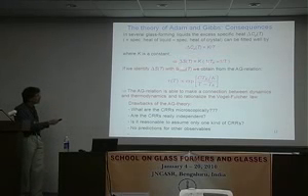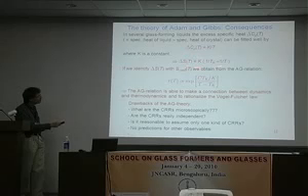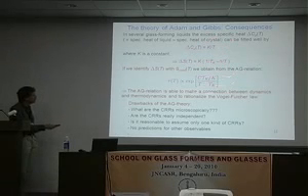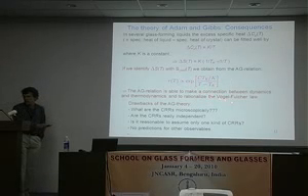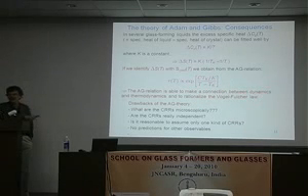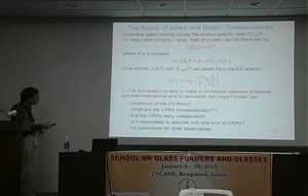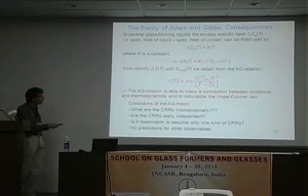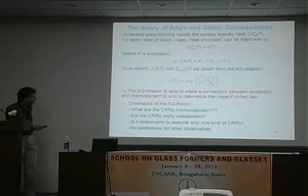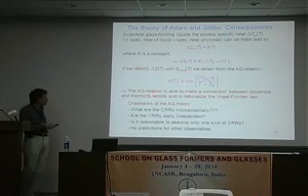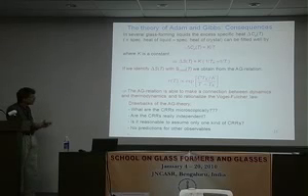You plug this into your entropy expression. You can calculate the specific excess entropy, which is given in this. You plug this into the Adam-Gibbs relation, and you get out this. And this is the Vogel-Fulcher law. So again, something which seems to work quite well, Vogel-Fulcher law, you can reproduce with this theory. And therefore, this Adam-Gibbs relation, as simple-minded as it seems, seems to have some of the truths of real glass forming liquids.